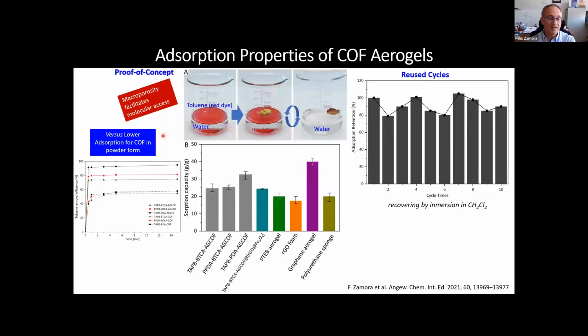Okay. So what we can do with these aerogels, just as a proof of concept, we decided to use our aerogels in this simple experiment in which we try to remove toluene from contaminated waters. And here we treat the toluene, which is on the top of the water, with a red dye just to facilitate the identification of the toluene. And then on the top of that, we put our monoliths, the three monoliths. And after several cycles, we observed that we were able to remove the whole toluene from the contaminated water.